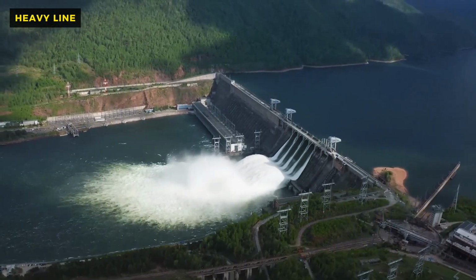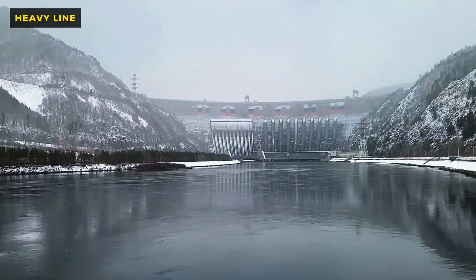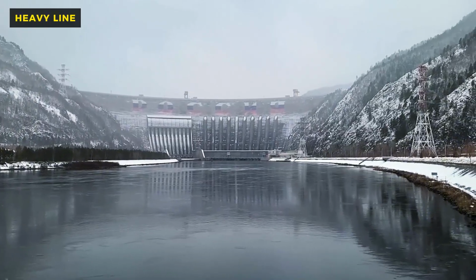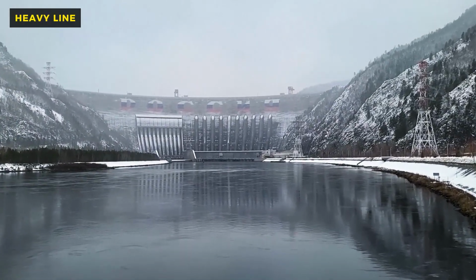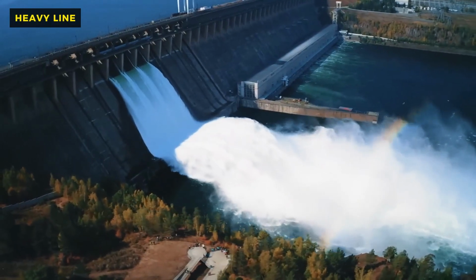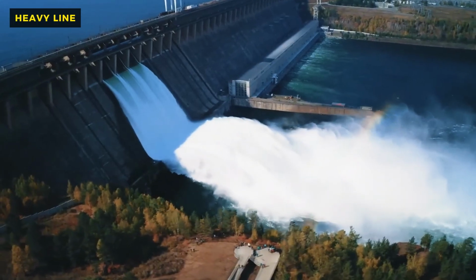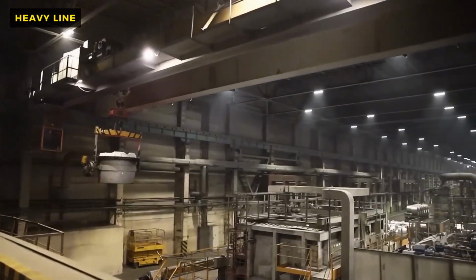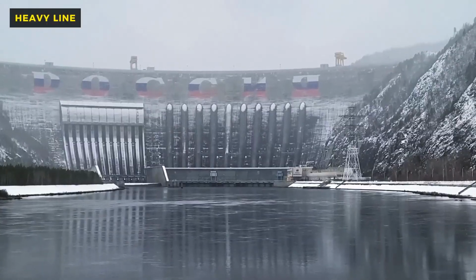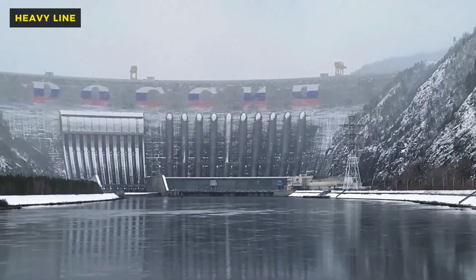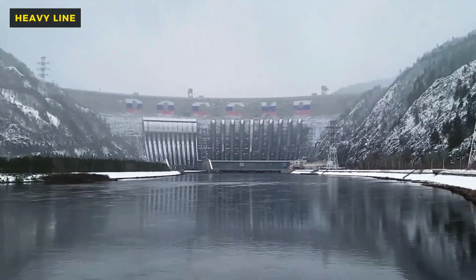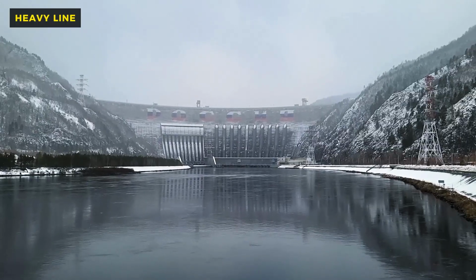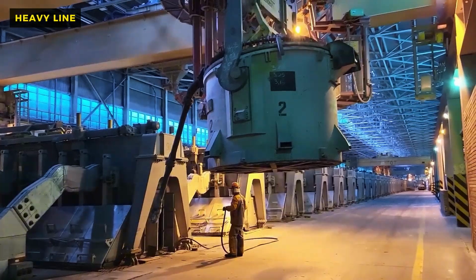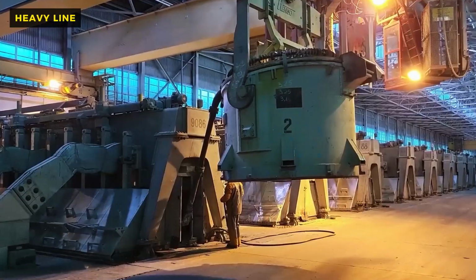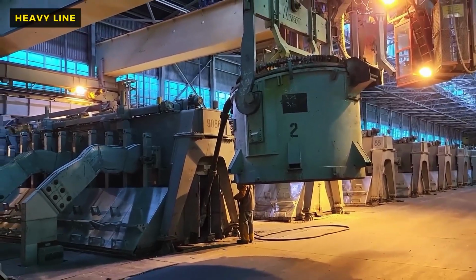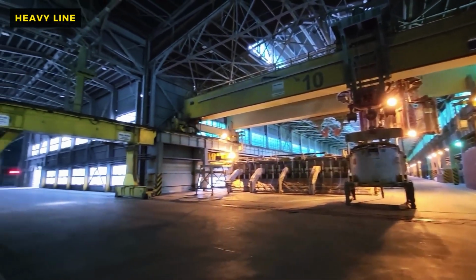The production of the anodes themselves is a factory within a factory, a dirty, gritty process that contrasts sharply with the high-tech precision of the control room. The carbon plant takes petroleum coke, a byproduct of oil refining, and mixes it with coal tar pitch to form a hot, sticky paste that is vibrated and pressed into massive blocks. These green anodes are soft and non-conductive, so they must be baked in colossal gas-fired ring furnaces for weeks, slowly heating up to 1,200 degrees Celsius to carbonize the pitch and fuse the structure into a solid, conductive brick.